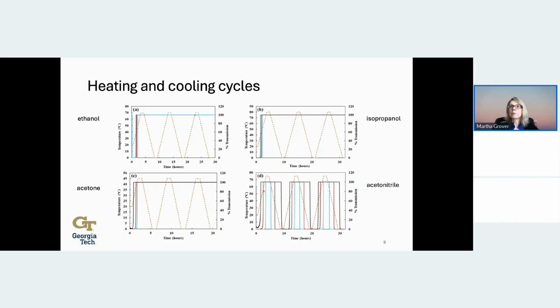And we can notice that when we heat in the acetonitrile, we get behavior in each of the 3 cycles upon heating that looks quite similar. Each of these cycles looks pretty similar. We're actually trying to crystallize a different form. But on the 2nd and 3rd cycles, we probably don't have the monohydrate because there's not very much water there. The water concentration is very low. But we really don't see major differences in the solubility. So we thought that was interesting or notable.